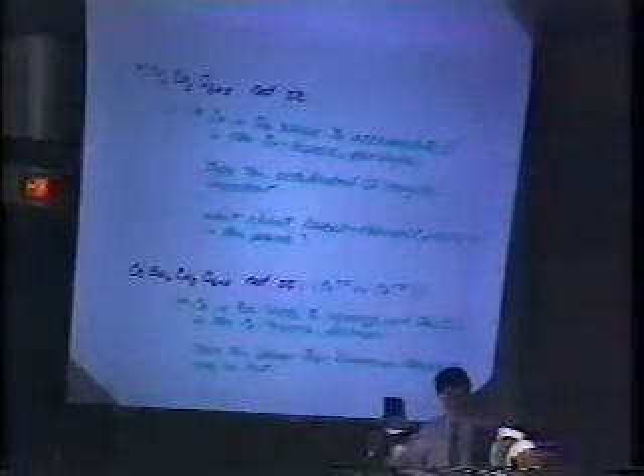And we also did the following. We looked at the yttrium barium copper oxide, but so far we have not been able to make it superconducting, although we got the majority phase to be the 1, 2, 3 phase. If this is true, perhaps the barium is too small to accommodate the oxygen in the barium layer. If that is true, then the octahedral oxygen must be important in contributing to superconductivity. And then we also tried cerium, and it doesn't work. It is possible that cerium is too large, but of course it can also go into the +4 phase. If that is the case, then the quasi-two-dimensional character may be important. We all know it's very important.